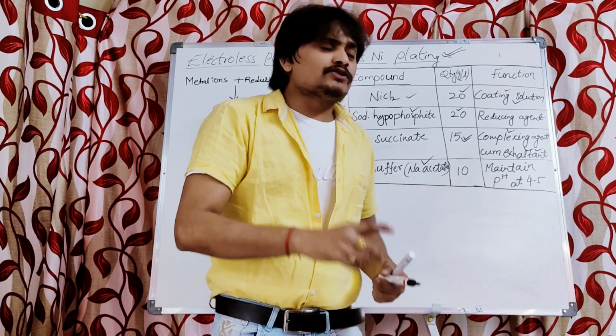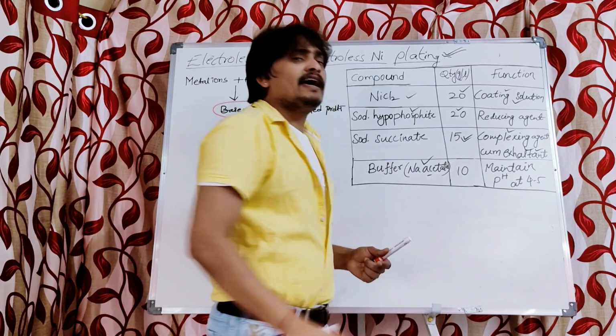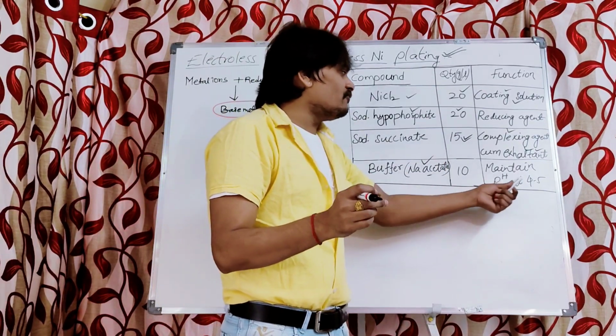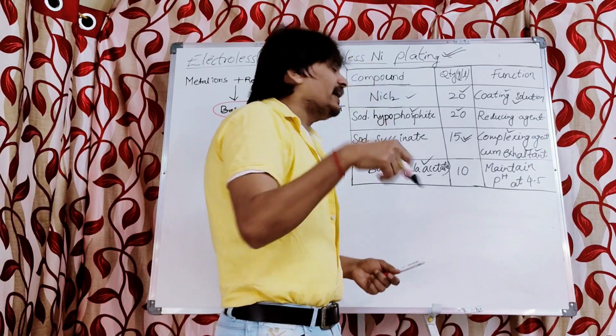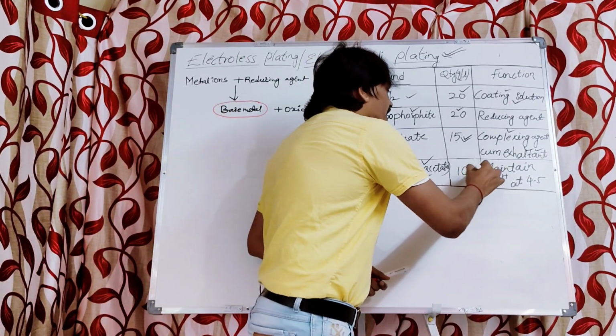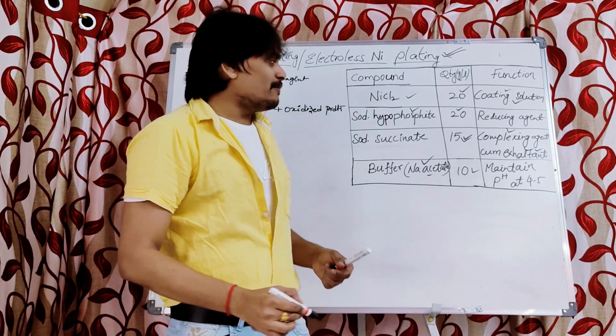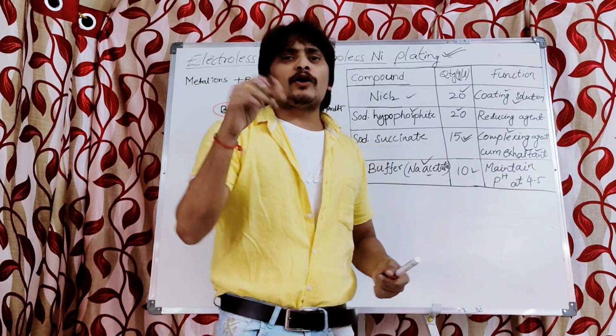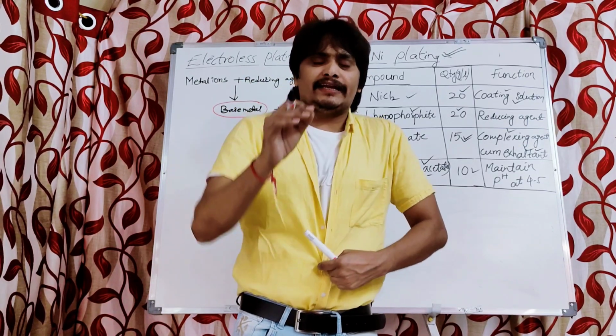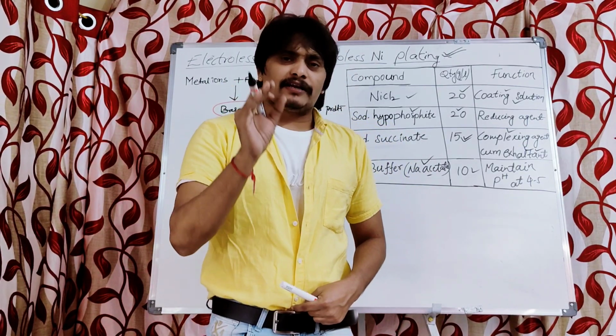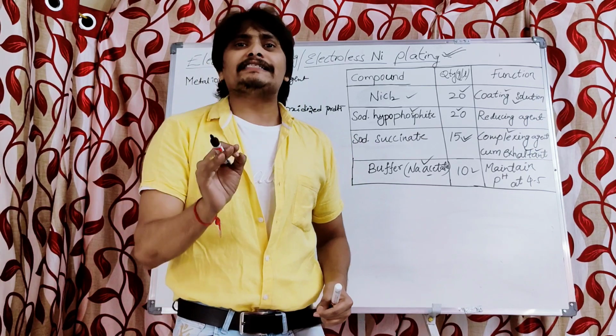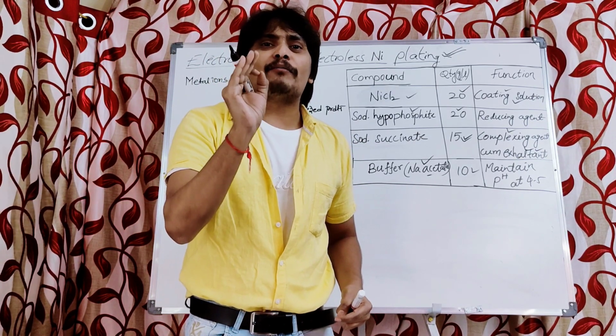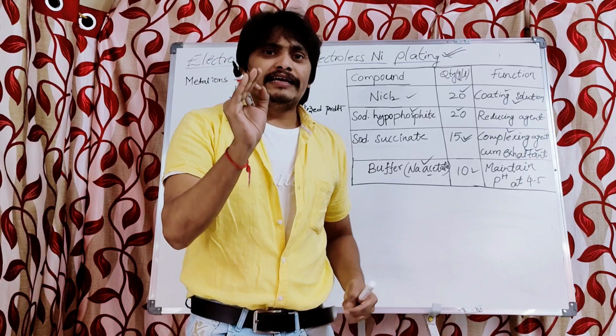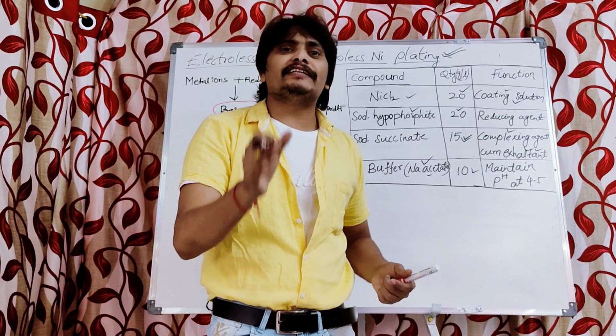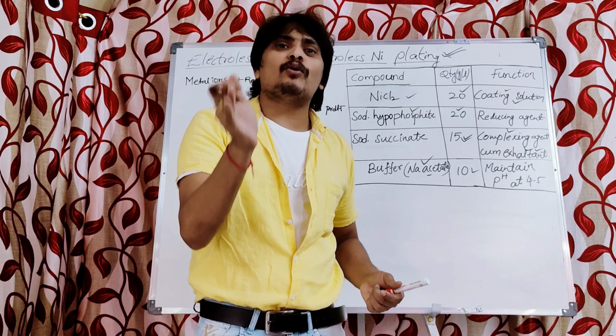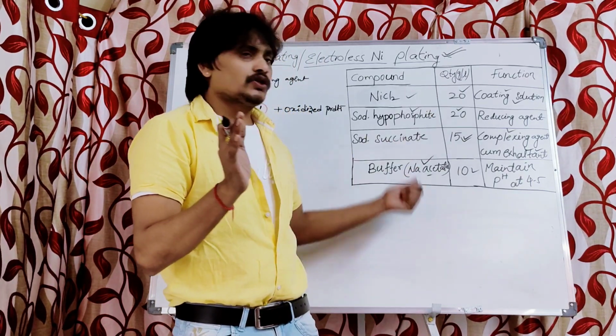Now, here the buffer solution is the sodium acetate, and it will maintain the pH at 4.5, and its quantity should be 10 grams per liter. Right. And not only that, apart from this, we have to maintain the temperature during this particular electroless plating. That is, 93 degrees centigrade of temperature should be maintained inside the bath in order to facilitate the reaction between the reducing agent and the coating solution. I hope you understood this.